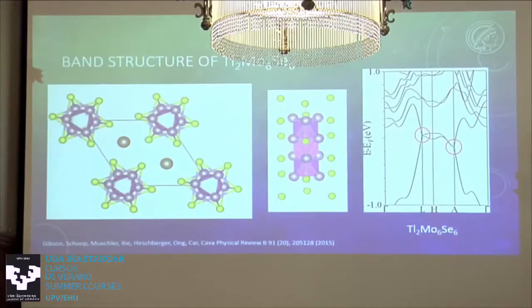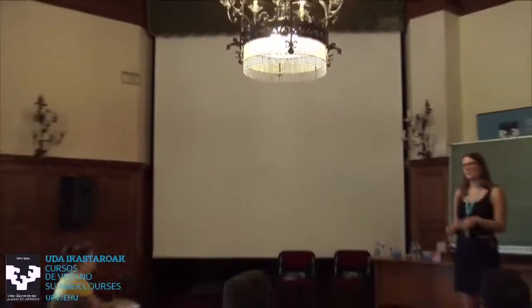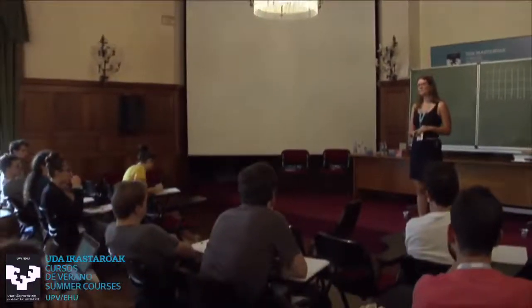And then if you calculate the electronic structure of that, you will see that there are the non-symmorphic points relatively clean, relatively close to the Fermi level. Still not perfect, but maybe this is really an idea of delocalizing this half-filled band over a large cluster amount of electrons to get these materials established. And this is the end of my first lecture. And then in the second one, I will give you some more examples of compounds that work.